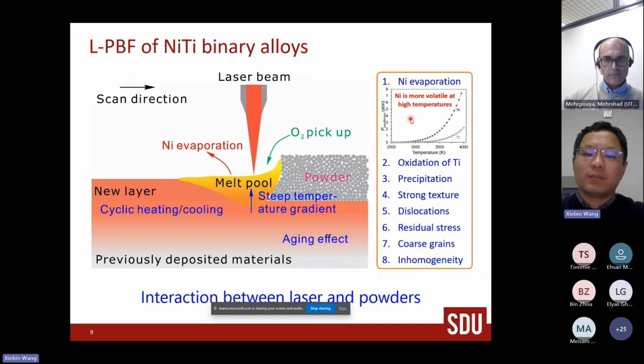After the additive manufacturing process, the parts will have a lower nickel content than the powders. And of course, there will be oxidation of titanium elements and precipitation of nickel 4 titanium 3 particles, titanium 2 nickel particles, and also other particles. And for additive manufactured parts, they show strong texture, high density of dislocations, and high residual stresses. And of course, you will get columnar grains and microstructure inhomogeneity. For all these factors, we found that the first one is the most important factor influencing the transformation behavior and the functional properties of nickel titanium alloys.